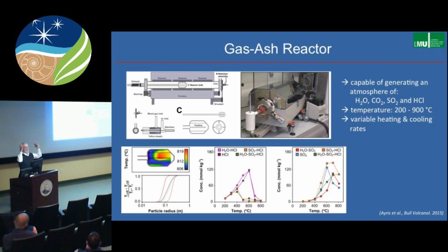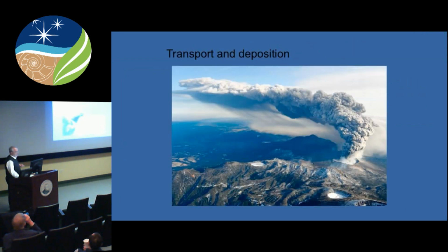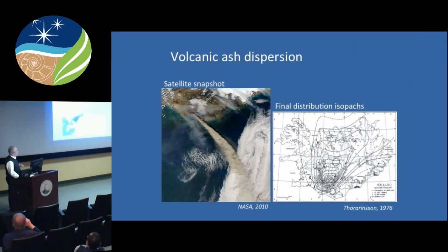We all know that the rock to sulfur ratio of eruptions varies widely. It's one of the reasons we started doing this. And we think we have a mechanism that might help us to explain why in some eruptions you sequester a lot of sulfur and some very little. And it probably has to do with the residence time in the conduit in those critical tens of seconds before the ash gets out. If you can sequester enough of it on the surfaces of the ash, it just gets dumped down in the valley and doesn't contribute to sulfur in the atmosphere.